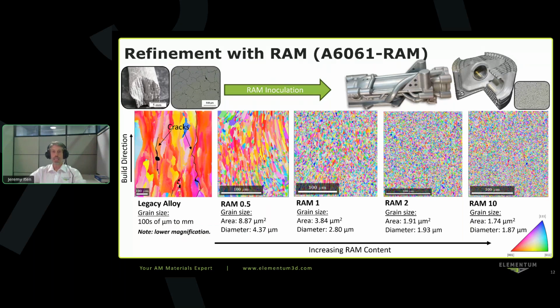However, you do get increased properties based on the composite that you're forming. So you get the benefits of both the ceramic phases that you're forming as well as the metallic phases. So you can increase your stiffness, your strength, your high temperature properties, and so on. So this is where you could also do a RAM 5 or a different RAM content to really target the exact combination of stiffness, strength, high temperature performance, ductility, and so on that you're looking for.